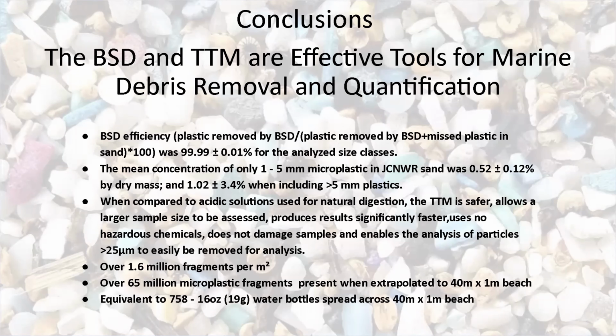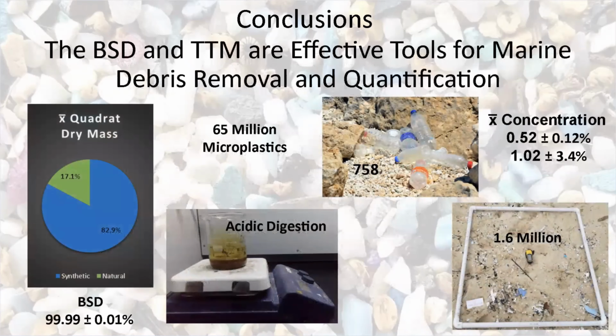So in conclusion, again, going over everything with you, 83% of that material that we removed from our BSD or from our beaches was synthetic, was plastics. The BSD had a 99.99% efficiency of removing microplastics down to 25 microns and larger. Per quadrant, there was 1.6 million pieces or more in that chamber. That equates, when we extrapolate to the 40-meter beach, to over 65 million microplastics, or 758 water bottles. In mean concentration, there's 0.52% of microplastics in our beaches, or 1.02% of marine debris on our shores.